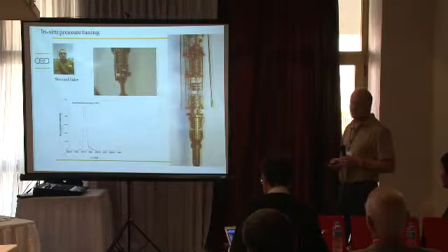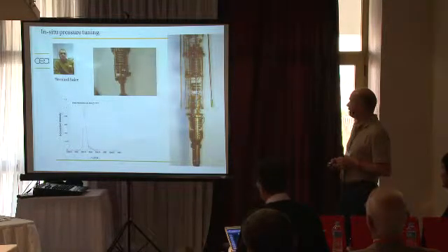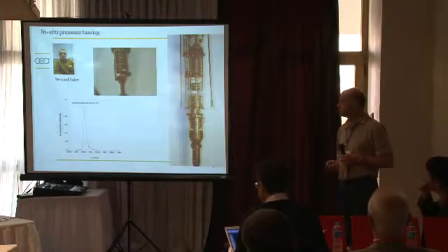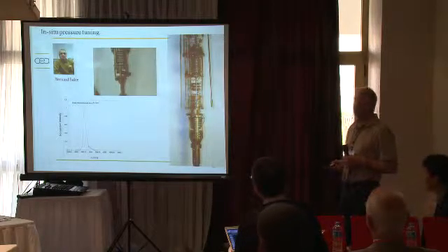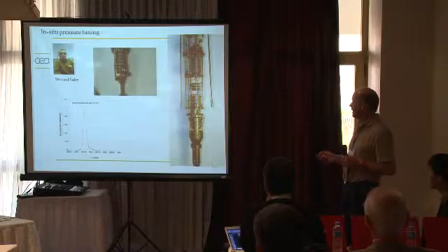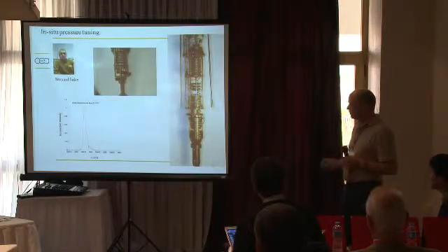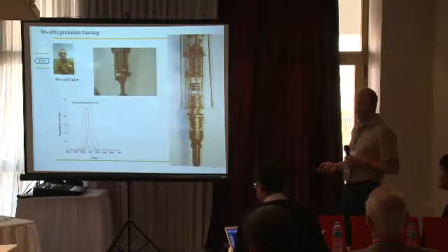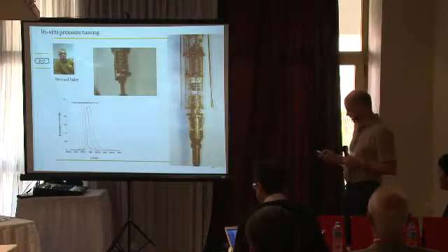We've always wanted to go a step further, and for the past few months we now have working a similar system on a dilution fridge. So we can do the same thing at very low temperature and also put on the magnetic field. Of course, if you change the pressure, you have to be able to measure the pressure. This is done with an optical fiber and the ruby fluorescence technique. So as you put pressure in your helium bellow, you can actually see the ruby peak moving and tune and get to the pressure you want.